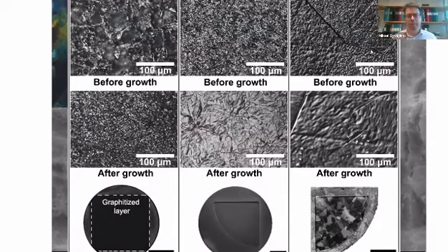On the left image, you clearly see that it is graphitized. The whole surface is graphitized, which is very bad for the growth because it shows that it's uncontrolled. When we have another type of source, it's not as much graphitized, but still it's influenced. And on the right side, you see some other type of source where it's actually not graphitized at all. So this graphitization is not good from the growth point of view for the silicon carbide layers. But it is interesting from some other point of view.